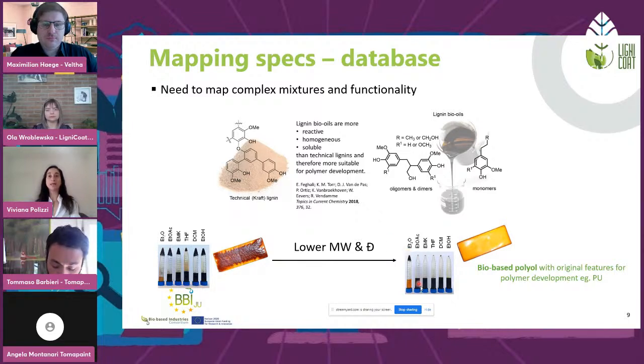In fact, you see here in the slide below that by applying depolymerization and using these fractions, we are able to increase solubility in different solvents. You can see that the residue in each tube is much less, or almost gone, compared to the original lignin. And we are able to obtain, here we give the example of a final material, a polyurethane.